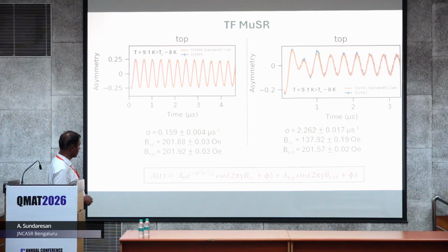These are the values, but still this is not complete. We try to use the single sigma, and the external field was about 200 oersteds. What we see in the superconducting state, it's the same field as in the paramagnetic state, but when you go to the superconducting state, it reduces to 137.